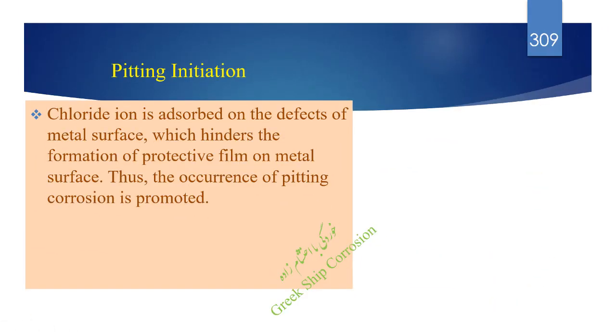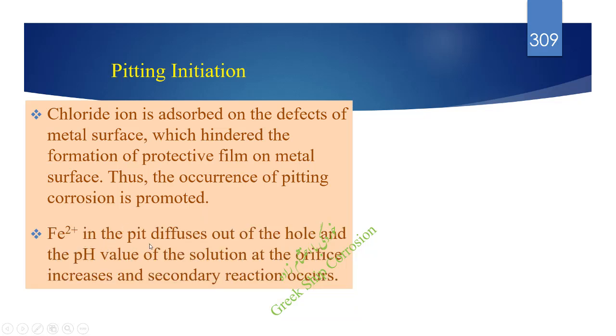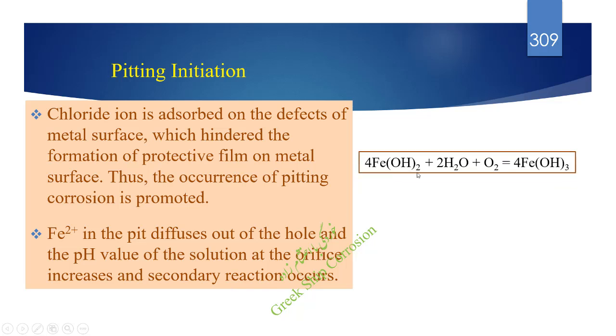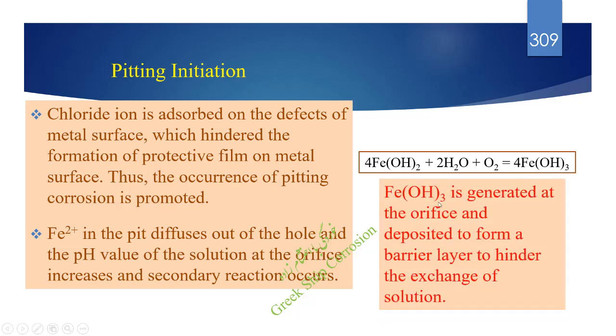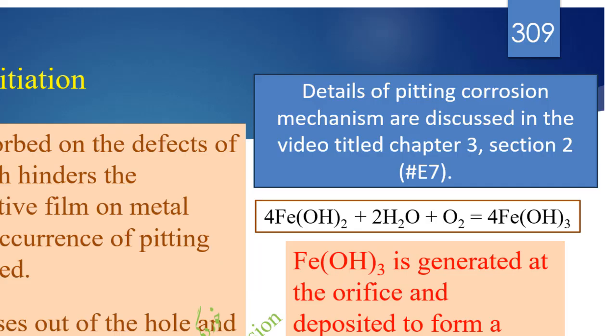Chloride ion is adsorbed on the defects of the metal surface, which hinders the formation of a protective film on the metal surface. Thus, the occurrence of pitting corrosion is promoted. Fe2+ in the pit diffuses out of the hole and the pH value of the solution at the orifice increases and a secondary reaction occurs. 4Fe(OH)2 + 2H2O + O2 equals 4Fe(OH)3. Fe(OH)3 is generated at the orifice and deposited to form a barrier layer to hinder the exchange of solution. Details of the pitting corrosion mechanism are discussed in the video titled Chapter 3, Section 2, number E7.